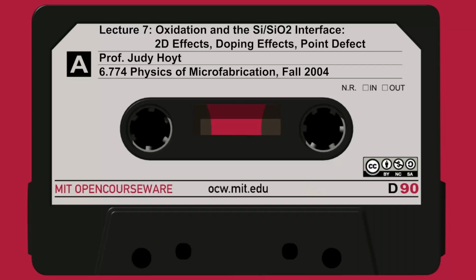And so that's quite convenient, because then you could use this to form reasonably uniform wires. Let's say lithography is not perfect, right? Some of the dots came out when he patterned it 200 angstroms, 250, maybe 210, something like that. Litho's not perfect, but he could get a reasonably wide range in the starting pillar diameter, and the final pillar diameter, if you oxidize it long enough, was pretty darn uniform, which was kind of nice, because you have a process now that's physically slowing down as it gets smaller. And so they all end up, even though you have a large distribution to begin with, very close to a single diameter. If you're trying to make some device or some interesting quantum thing, that was a very nice side effect.